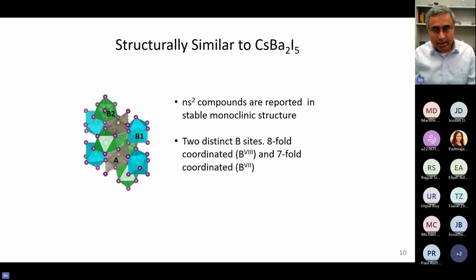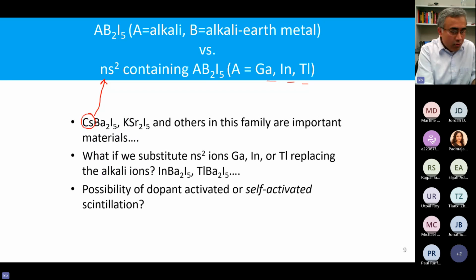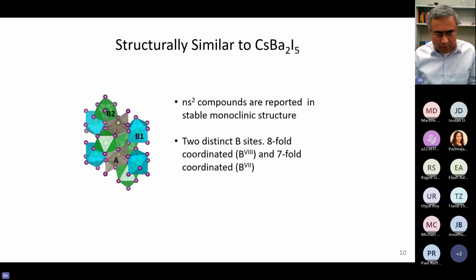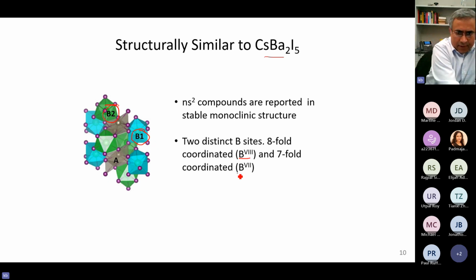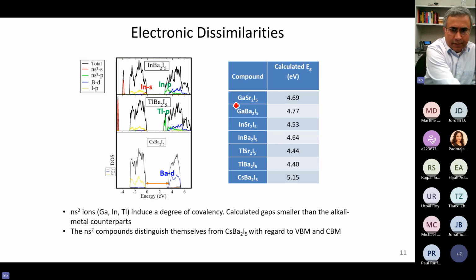So what we did is, instead of cesium, we are now looking at, let's say, indium barium iodide or thallium barium iodide, replacing the cesium with a thallium or an indium. These materials exist. We found them to be stable. Again, the structures are similar to cesium barium iodide, monoclinic structures. So you have two kinds of site, one 7 coordinated, one 8 coordinated. Let's call them B1, B2, or B8, B7, whatever way you want to call them. Just that those two distinct sites are there for barium. And then we did all these sets of different compounds with different Ns2 atoms and compared with our original cesium barium iodide right there.